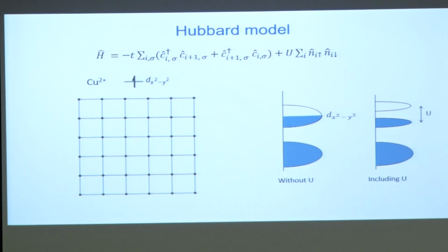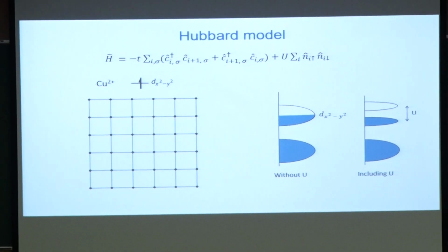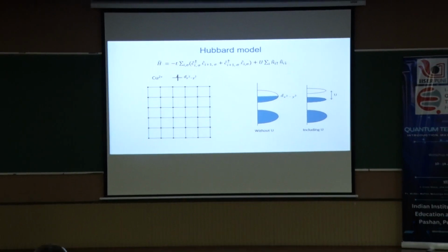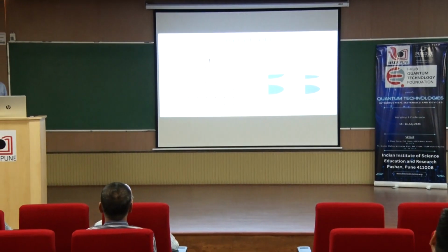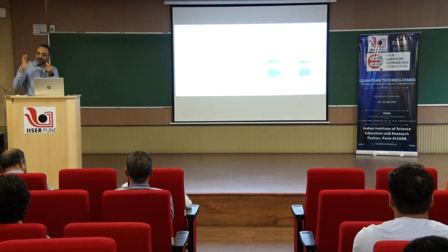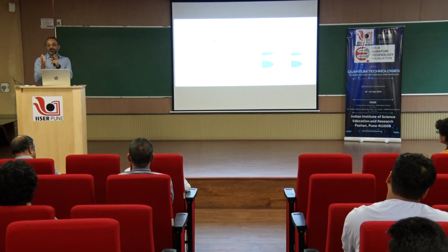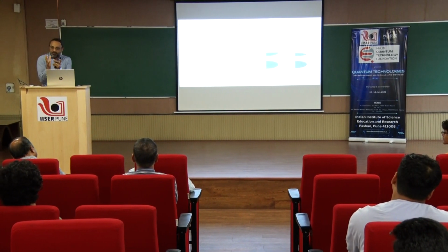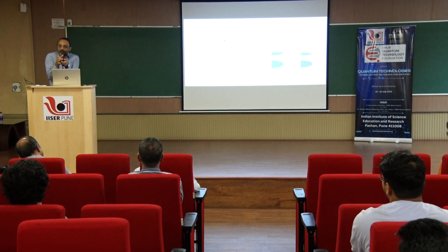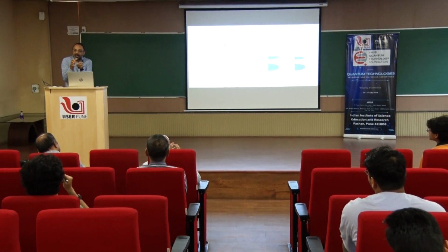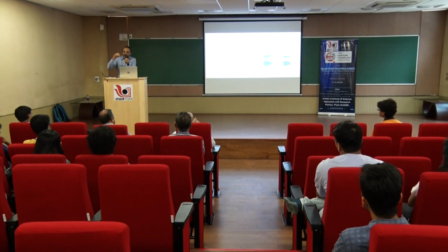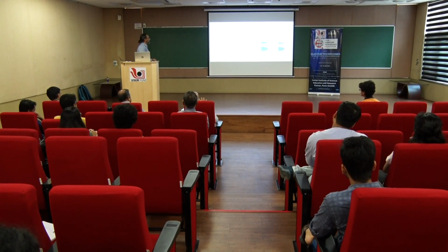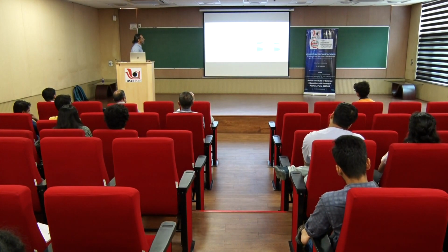So, therefore, the material will behave like an insulator and not like a metal, because for it to behave like a metal, the electron should be able to hop from one site to the other, and that will happen when U is 0. If you make U 0, then of course you have a half filled band, but if U is non-zero, then there is a competition between the T term and the U term. The U term is trying to keep the electron at its respective site. It is preventing the electron from hopping from one site to the next. So, this is depicted here in this form.